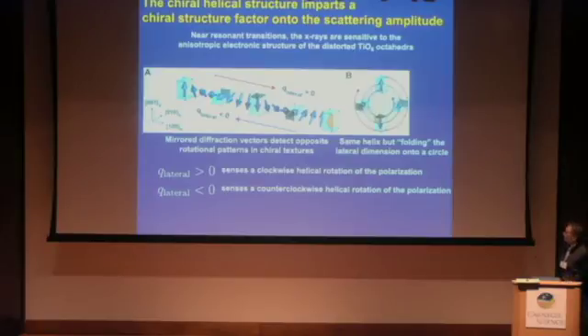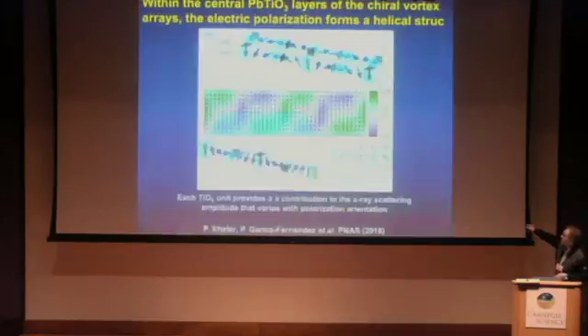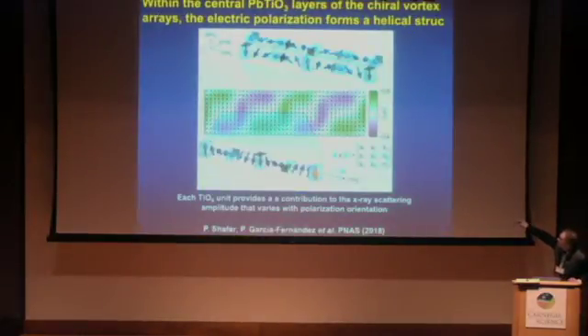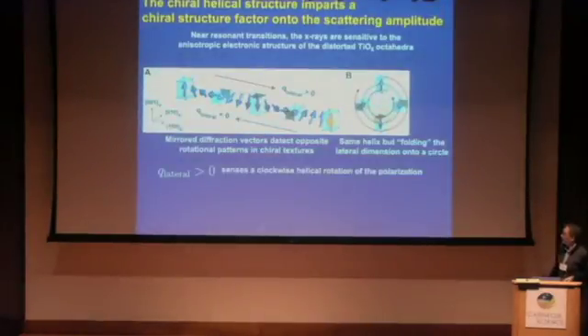So the origin for this chirality can be traced back to the presence of a helical structure here at the center of the clockwise, counterclockwise vortices. So if we just plot a line here and look at how the polarization is changing, we can see how we have a helical structure.